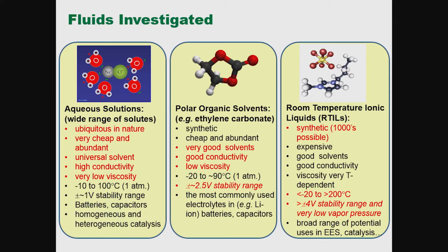Organic solvents expand that voltage window with a lot of the good characteristics, but they're flammable and they're volatile. Ionic liquids are expensive, but they have this really nice temperature stability range. They have very low vapor pressures, almost no vapor pressure in many cases. And they have this potentially very large voltage stability window, which Majid mentioned very nicely this morning.